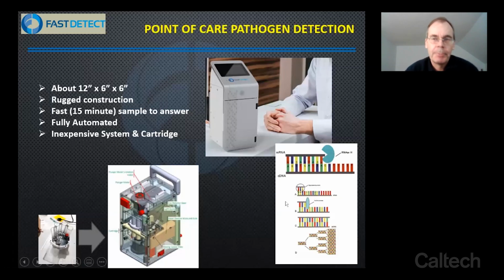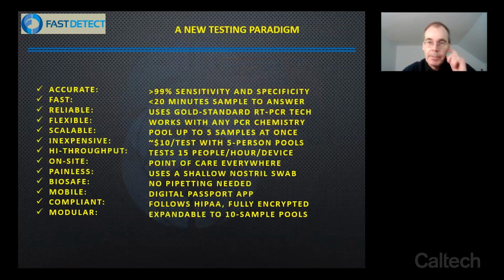And to remind you what PCR does, polymerase chain reaction, it actually amplifies the number of molecules. So if you have DNA, you can heat it up to 95 degrees, and it splits from its double helix structure into 2 single-stranded molecules. And then when you cool it back down to 55 degrees in the presence of an enzyme and a template or primer, then you can essentially amplify and double the number of molecules every time you heat and cool. So in a system like this, it's important to do this very quickly because we want to do this in 15 minutes so the patient doesn't have to wait.